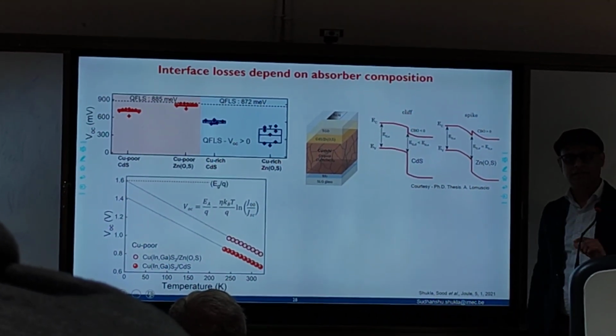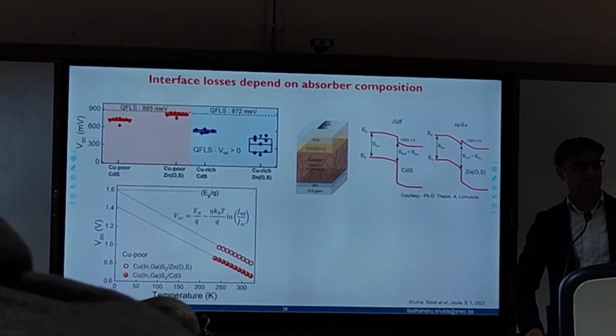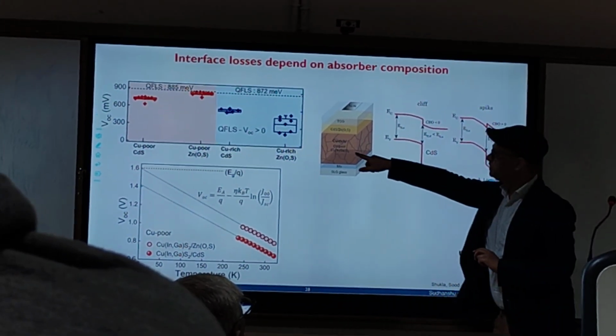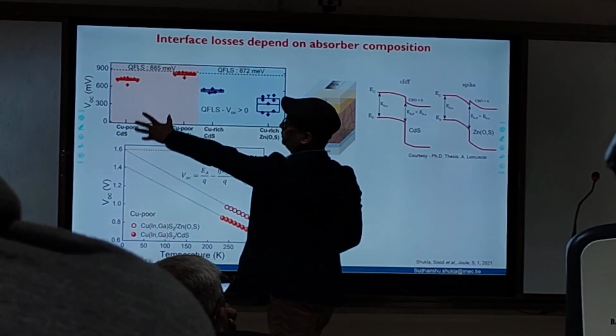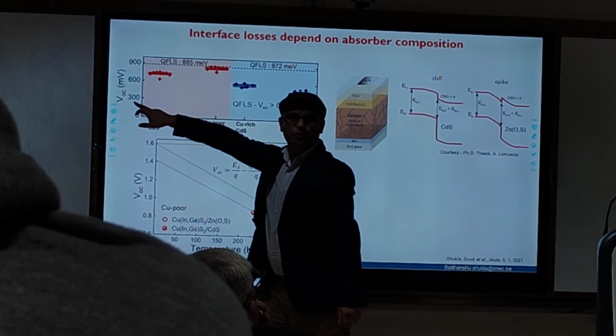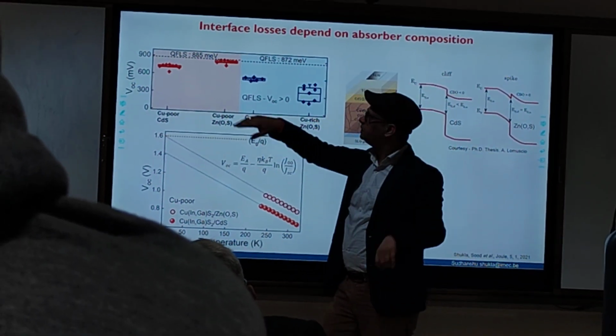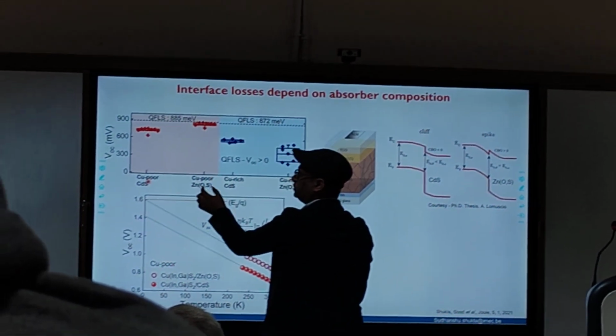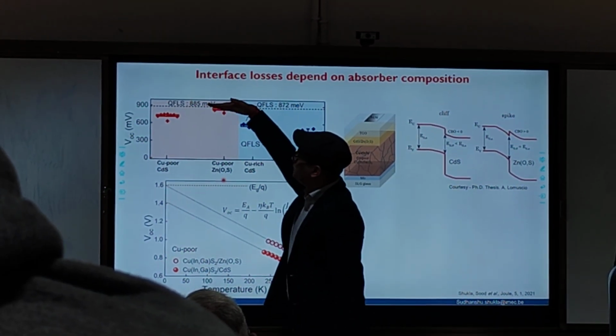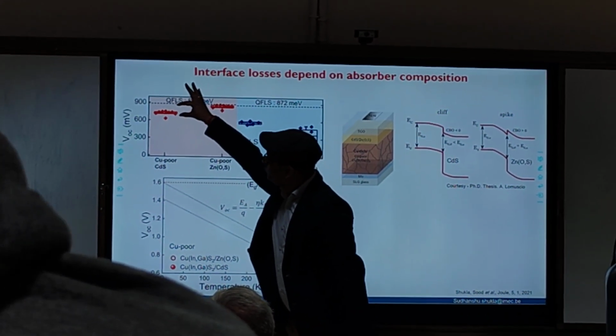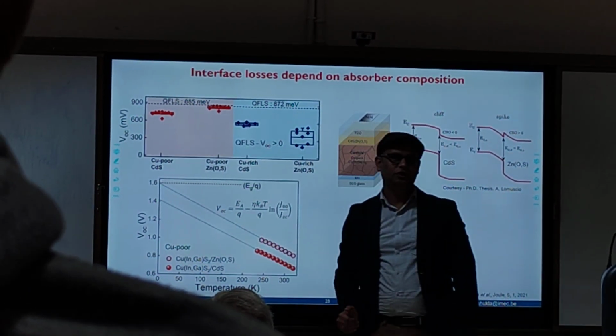Let's see. As I said, interface is governed by the p-n junction, so the n partner is very important. For CIGS, the n-type partner is cadmium sulfide or zinc oxysulfide. Okay, this is the copper poor regime. You see, the VOC that you obtain of your solar cell device is close to the quasi-Fermi level splitting, which means less interface recombination for zinc oxysulfide. So when we change from cadmium sulfide to zinc oxysulfide, our VOC matches with the quasi-Fermi level splitting. No loss at the interface. But when you have cadmium sulfide, there's a lot of loss at the interface, boom, your VOC comes down. It's because cadmium sulfide is not a good partner.